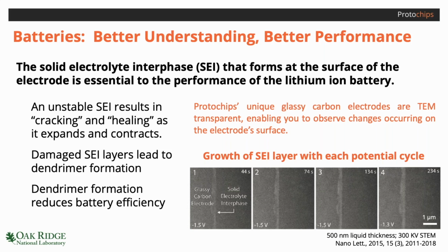In this example, researchers at Oak Ridge National Lab studied the growth of the SEI layer over a series of potential cycles. The image series shows the growth of the SEI layer that forms between the electrode on the left side of each image and the electrolyte on the right side of the image. The SEI layer is the light colored line in the middle of each image, and its density and area increases with each subsequent potential cycle.